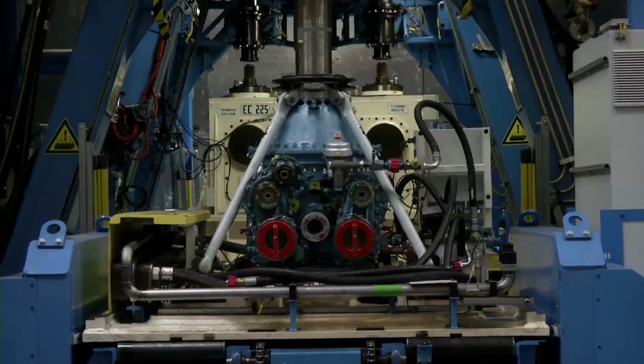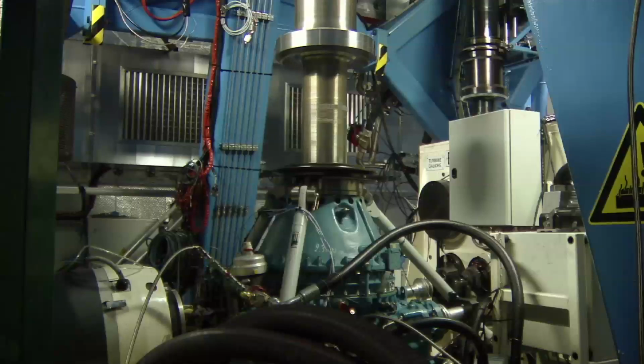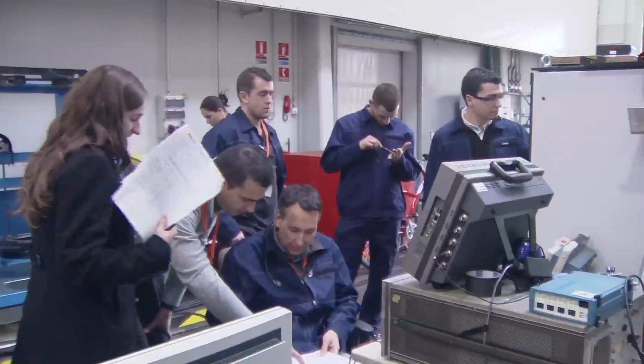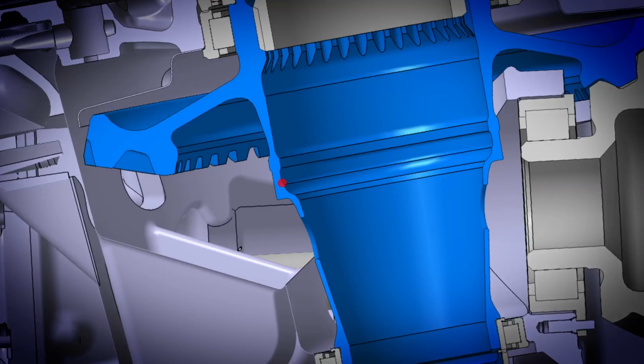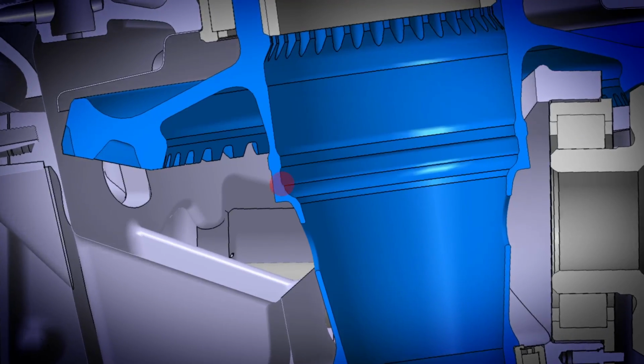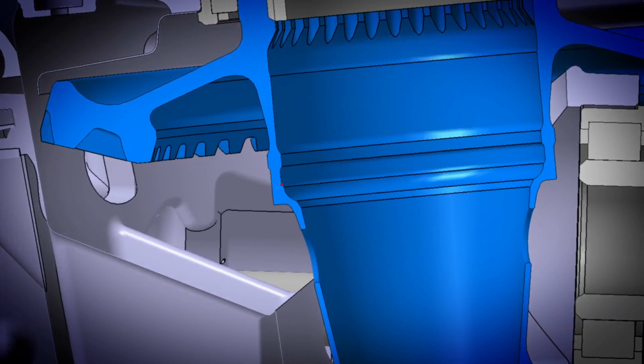The main factor has been identified and explained: the presence of moisture trapped in confinement of the welded area in direct contact with the bevel gear during in-flight solicitation. In the area where moisture is trapped, an exceptional phenomenon called active corrosion develops and grows over time, leading to a weakened material after several hundred hours of flight.